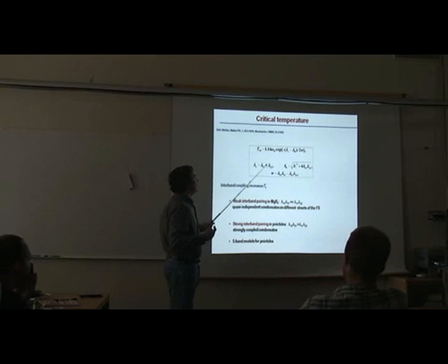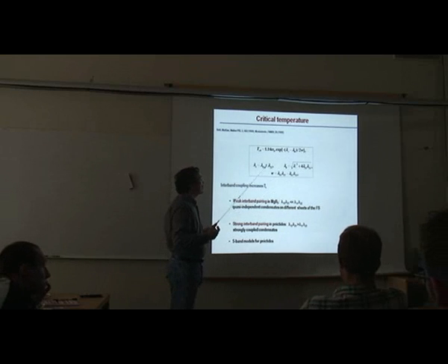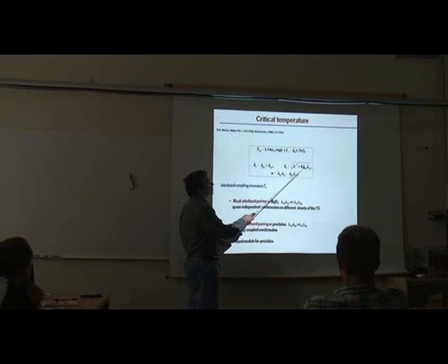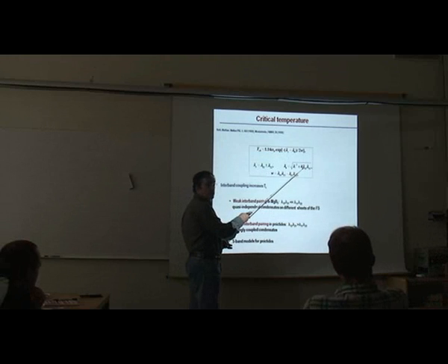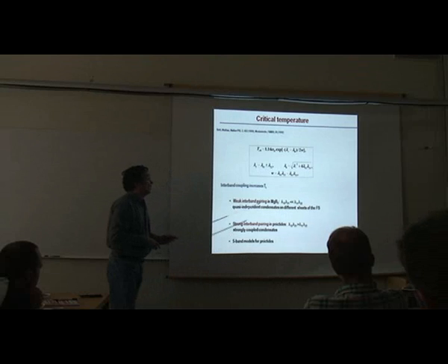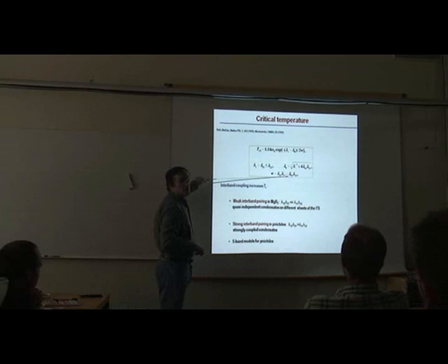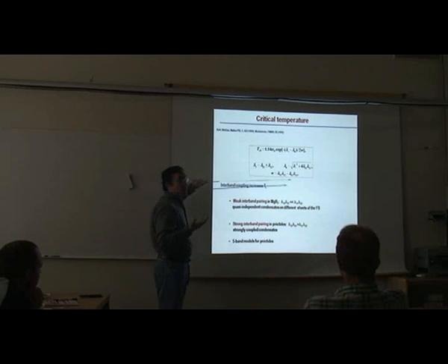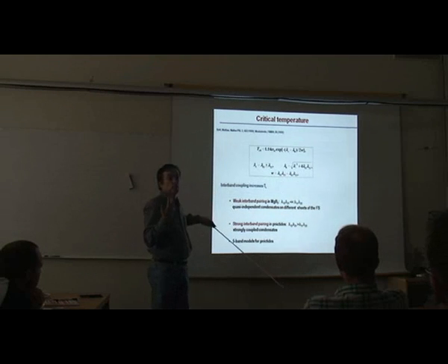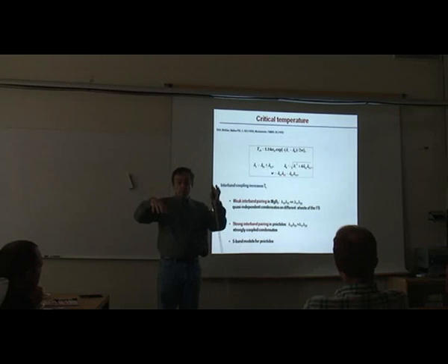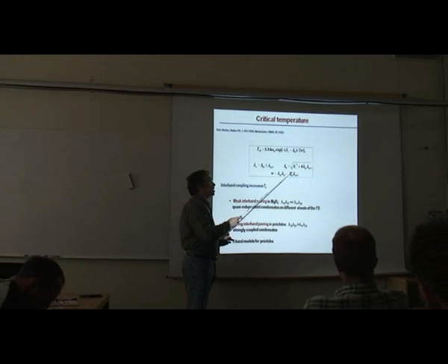And so you have the intraband coupling, and then you have interband coupling here and here. And you can see that because interband coupling comes in this combination, the sign doesn't matter. I can change the sign, and I still have the same TC. However, what's important here is that this determinant can be either negative or positive. So this determinant is positive for a conventional two-band superconductor like MgB2, for which superconductivity comes from Cooper pairing in each band, called pi and sigma band. And the interband coupling is weak, so this guy is small.